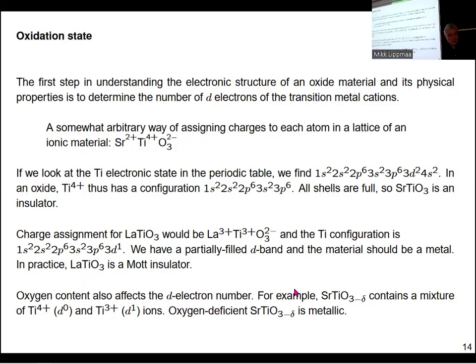Another important character is the oxygen stoichiometry. Many materials are not stoichiometric, strontium titanate or some other oxide. This delta here is crucially important. Some metals more easily than others can give up their oxygen. So if you would take, for example, strontium titanate and put it into vacuum and heat it to, let's say, 700-800 degrees, the normally white material, an insulator, becomes metallic. It turns black in color. And that is because it loses oxygen.